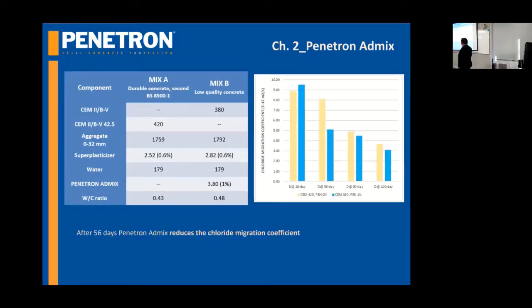We did the same thing with chloride, the resistance to chloride migration, and we realized the same as before: the low quality concrete with 0.48, but with the Penetron admixture inside, got a reduction of the permeability to chloride. So the coefficient of chloride migration decreases, especially after a long time. We can see after 28 days, it's higher. This is because the crystalline admixture still hasn't worked completely. The crystals are forming, and after that the reaction starts, and the chloride migration coefficient will decrease over time.